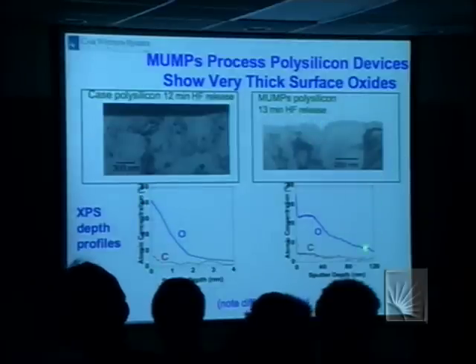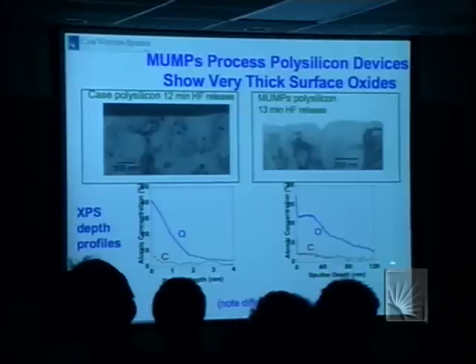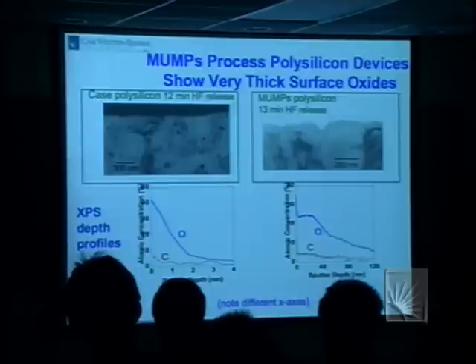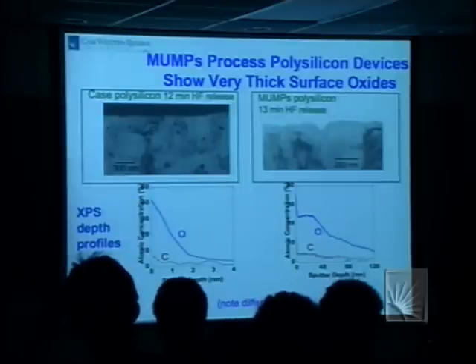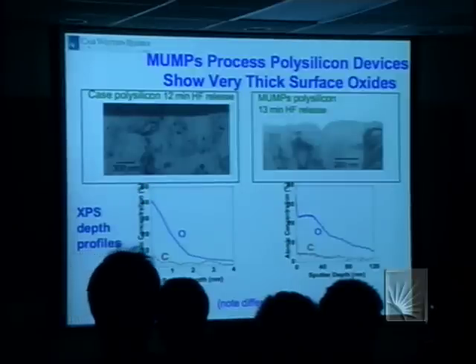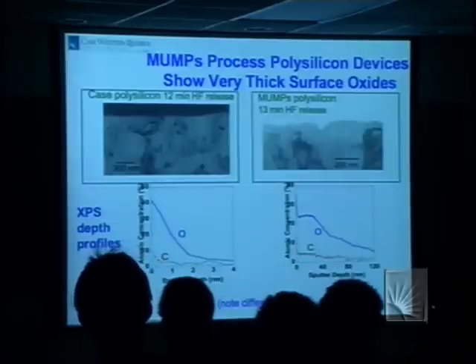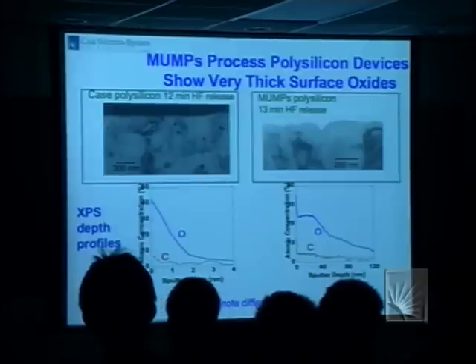On this MEMS sample, it's something quite different. Notice the scale. This is 40, 80, 120 nanometers, not angstroms, 1,200 angstroms. There's a very thick surface oxide. And you can see it's this wretched-looking stuff on the top of this piece of silicon. This silicon hasn't passivated. Very, very strange. No one has ever considered non-passivating silicon. Everybody knows, including all the MEMS engineers, that silicon just forms a native oxide, and that's the end of the story. Well, it's not the end of the story.